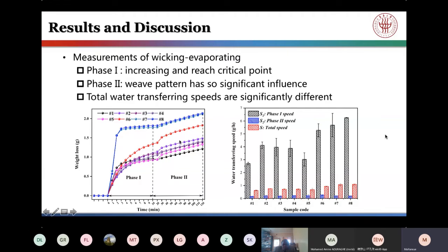Now in phase 2, the ANOVA results indicated that the wave pattern has no significant influence on the transfer speed. Well, the figure on the right shows the water transferring speed versus the sample. And the transfer speed in phase 1 and the total transferring speed shared a similar trend and varied significantly among 8 samples due to the large contribution of wicking to water transfer in phase 1, and the total water transfer speeds are significantly different among the samples. And this suggests that wicking dominates the whole water transfer process in the vertical wicking evaporating test.